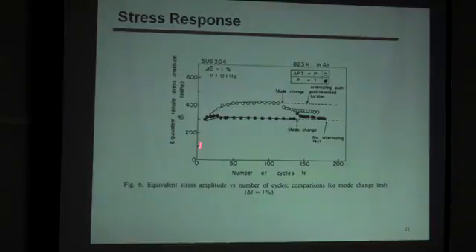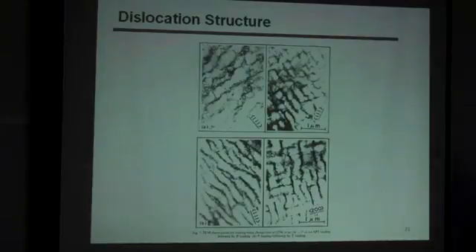That implies that once formed, the push-pull microstructure will rearrange under torsion. But on the other hand, for the material preloaded by APT non-push loading and switched to push-pull loading, the stress starts to decrease, but did not reach the push-pull level. That implies that the cell structure formed in the APT loading is very rigid, and we confirmed it by TEM observations. And my guess is true.